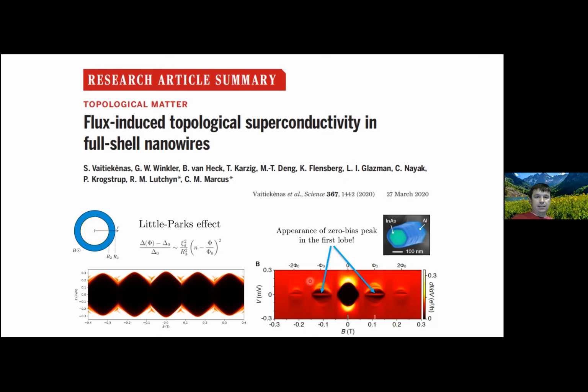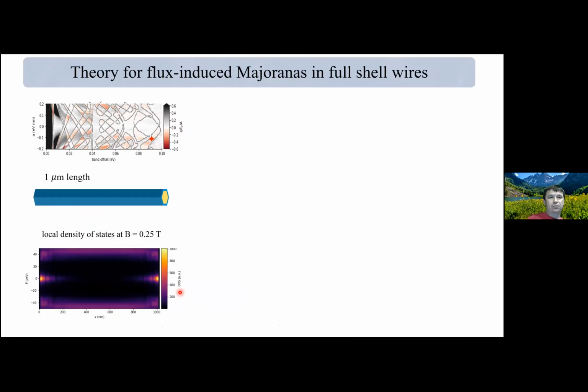The interesting observation is that when we have a magnetic field which corresponds to integer flux winding around the shell, there is a close to zero energy state appearing in the spectrum, and this state is not present when we just have an s-wave superconductor. And so the question was, what is the origin of this zero energy state? Is it some fine-tuned trivial state, or does it have any topological origin? That's where we came in, and we realized that this system has similar ingredients, has spin-orbit coupling, but rather than the Zeeman field, the dominant effect is the orbital contribution of the magnetic field.